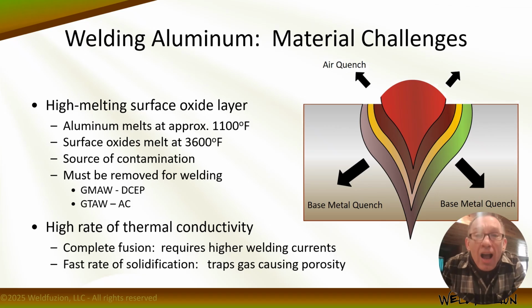Aluminum also has a high rate of thermal conductivity, so it's harder to form a weld pool and requires more current than steel because it's dissipating the heat from the arc at a faster rate. This fast rate of thermal conductivity means the puddle wants to solidify quickly, and that can trap porosity. So those are the things we're going to talk about as we move through general welding practices to get good results on aluminum.